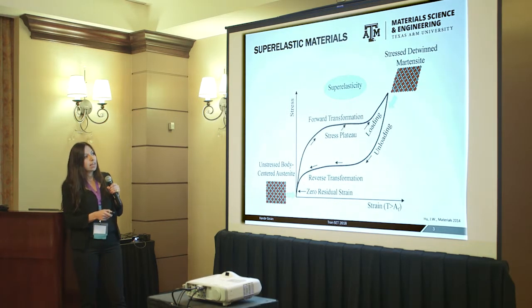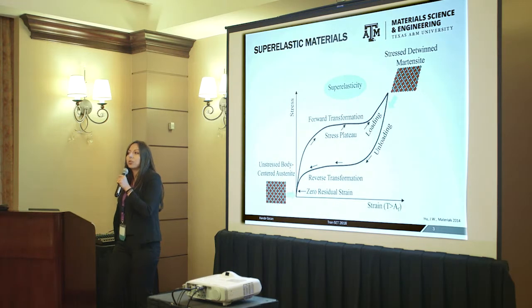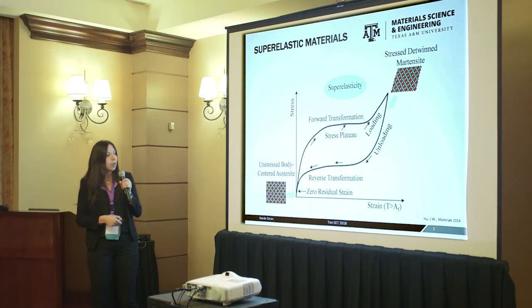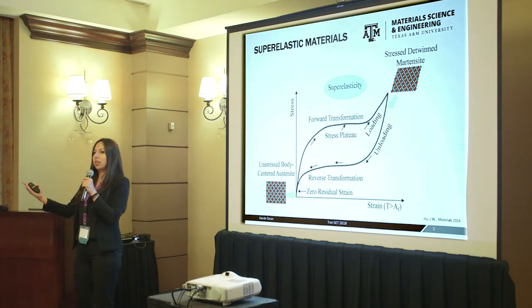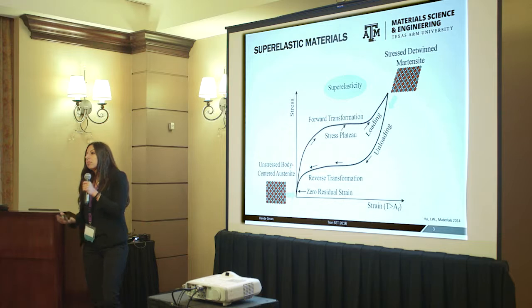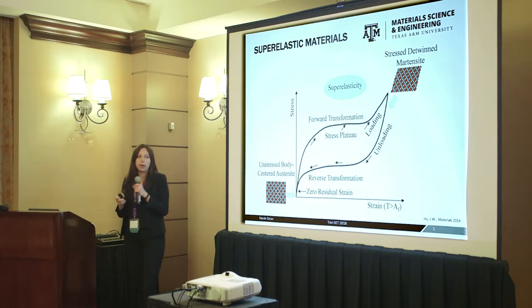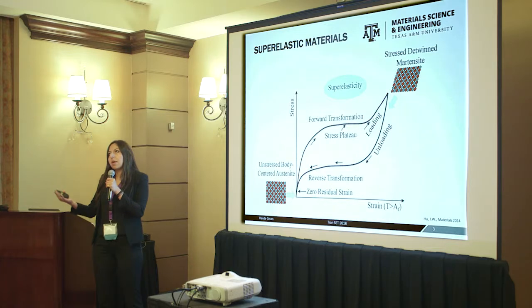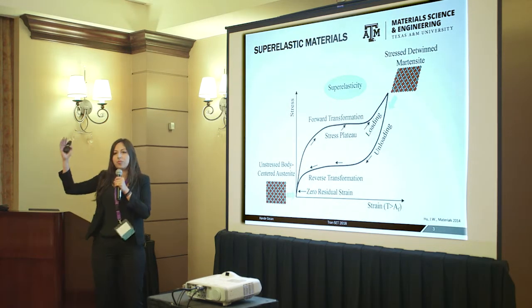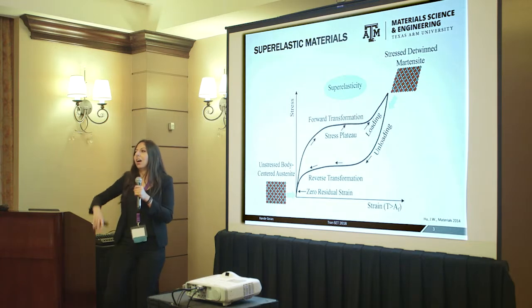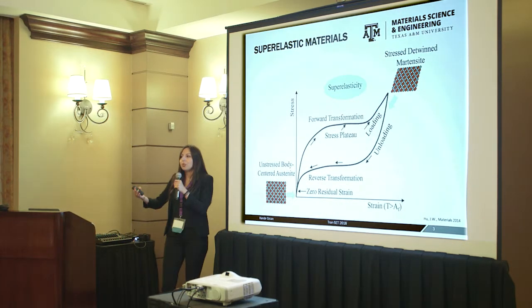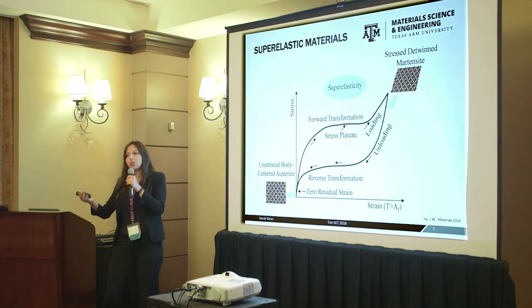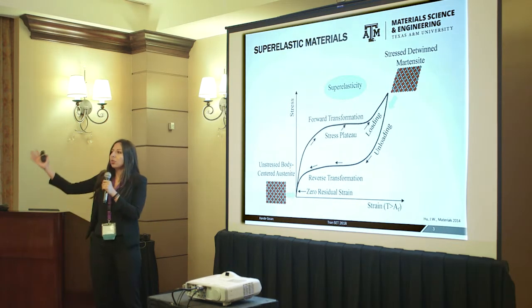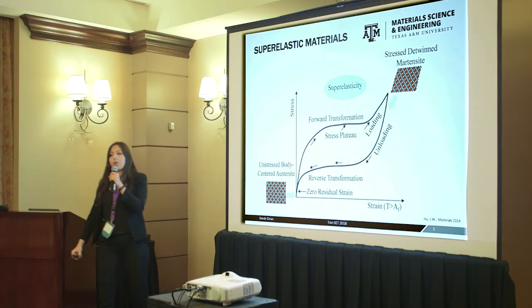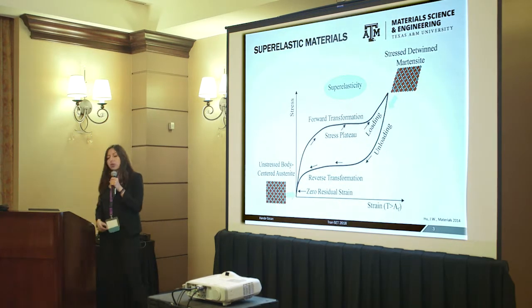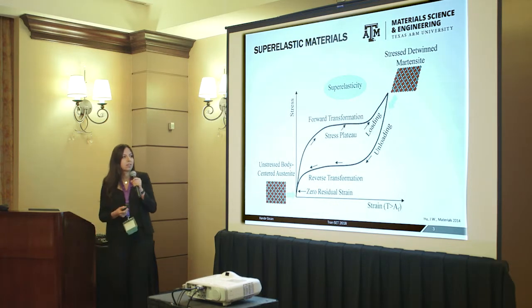And we can get up to 7 to 8% recoverable deformation from shape memory alloys, which will allow us to use this material as recentering structures in the civil engineering area. For example, imagine during a hurricane, a traffic sign; usually we see lots of pictures where the traffic signs have collapsed, right? But if you do use a shape memory alloy, you can still recover the deformation up to 7 to 8%. So they are very advantageous in that sense.